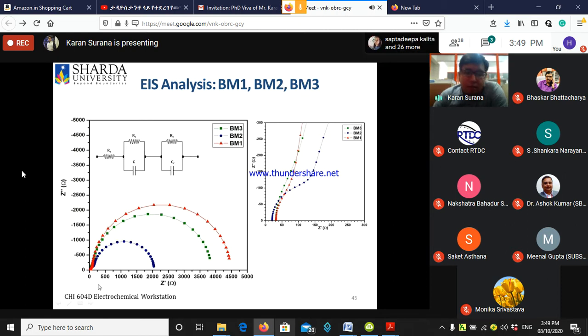Because of the use of a TiO2 layer and the graded structure of QDs, we can see that the impedance has gone down significantly compared to the other two cells, and this has again reflected in the solar cell characteristics, that is the efficiency, VOC and the current.